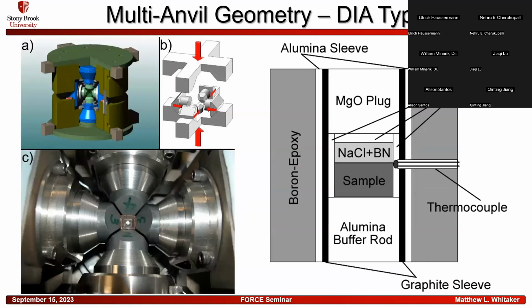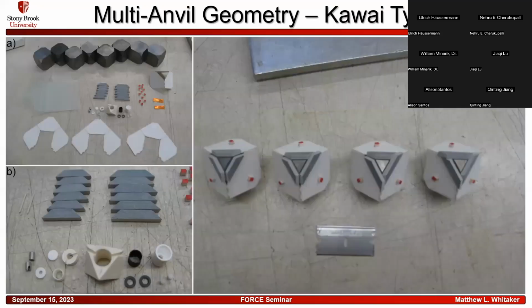And there are a couple of different geometry types that we're going to talk about today. This dia type geometry is what we have available at the 6BMB beamline. And this is a very simple cubic assembly that has 6 anvils that come together around a cubic cell assembly where your sample is centered in the cell. And everything squeezes together and you can form pseudo-hydrostatic pressure that way.